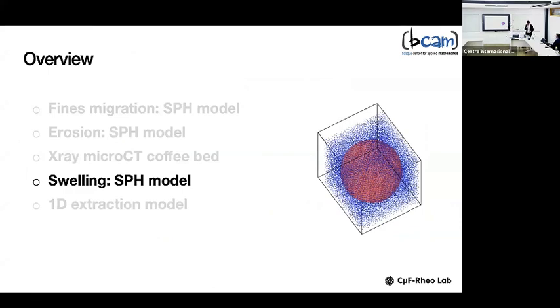Another thing that we have mentioned is the swelling. The swelling will be very important because water is imbibed. So coffee particles are imbibed with water, and eventually they will stretch. Stretching will produce swelling, and swelling will alter porosity and will alter flow rates, and therefore we will alter extraction kinetics.